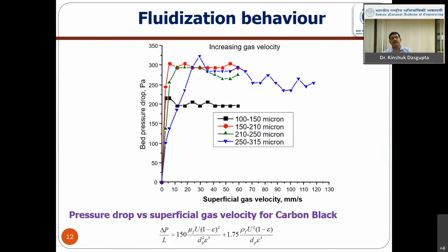So as I told, the fluidization is very much required. So we need to ensure whether proper fluidization is happening or not. So there is the famous Ergun equation, and if we perform this kind of study, if we measure the bed pressure drop against the superficial gas velocity, we end up with initially an increasing pressure drop, and at the beginning of the fluidization, the pressure drop just drops and then remains constant. So by this experiment, we can find out the minimum fluidization velocity, and we need to operate above the minimum fluidization velocity so that all the particles are in a suspension condition and we can utilize the maximum surface area.